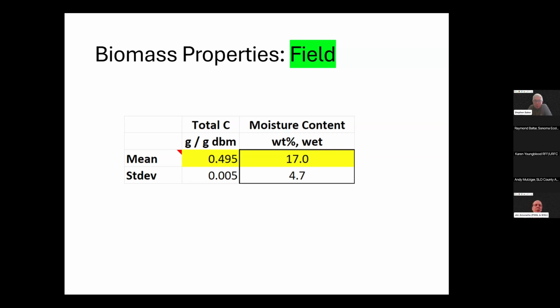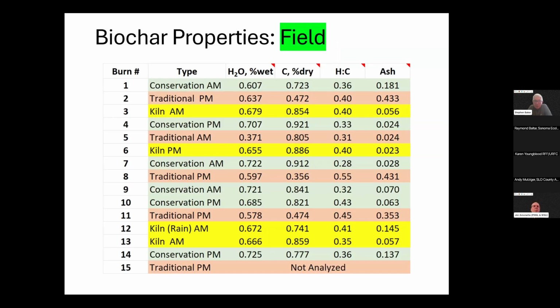So the biomass in the field is about half carbon, 49.5%. And the typical moisture content was about 17%, but there's a fair standard deviation on that, so we'll just keep that in mind as we proceed. For the biochar properties, we collected them for 14 out of the 15 field burns. I'll give you summaries later in terms of absolute averages, but just to give you an idea of what we did collect.